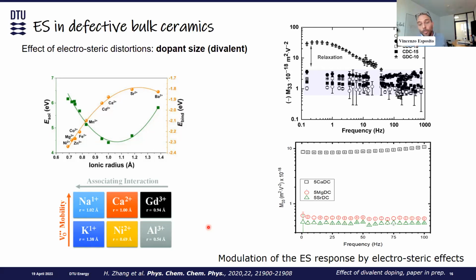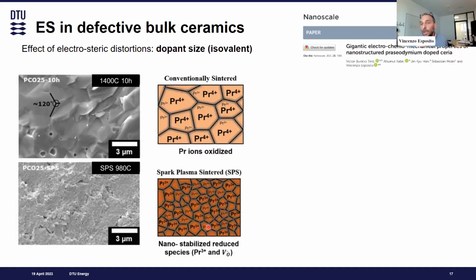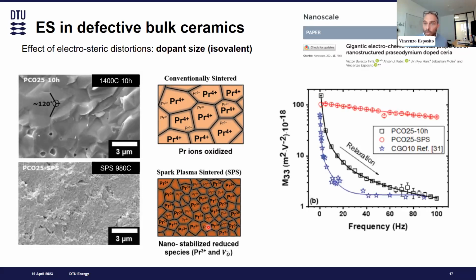So, on the other hand, it's also possible to manipulate the response, to have a material that has maybe a steady response in a different range of frequencies. Other important options are using isovalent dopants that can be tuned depending on the processing technology that you are using. This is the case, for example, of praseodymium-doped ceria, which is actually a pretty good electronic conductor at high temperature. It's not that good at low temperature, but when we use reducing conditions, so when we have a large population of 3+ praseodymium, we can get a very high electrostriction in a wide range of frequencies. And this is also very nice.